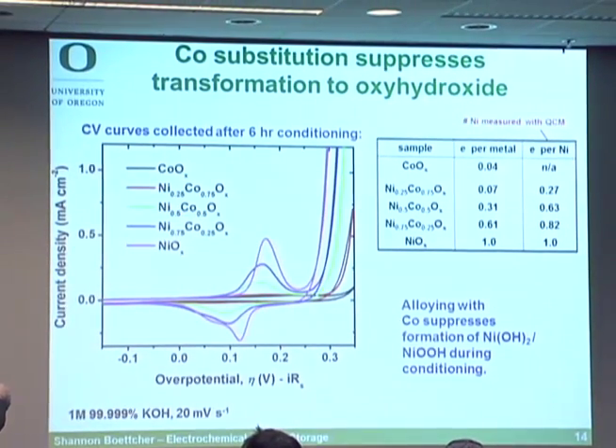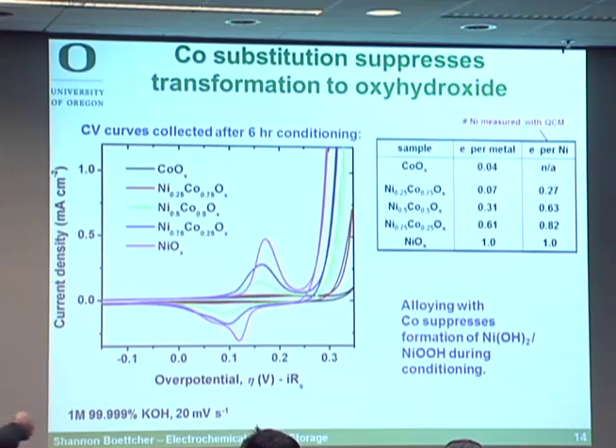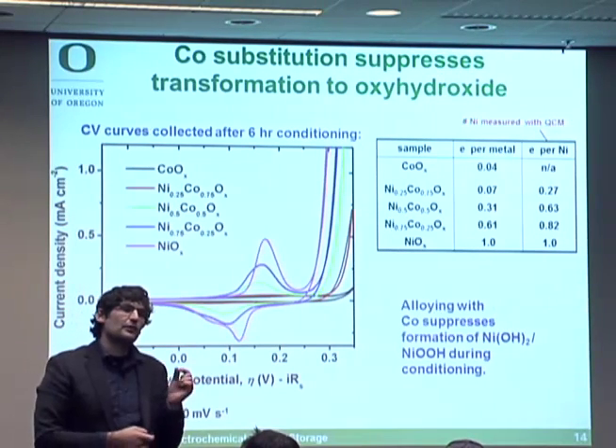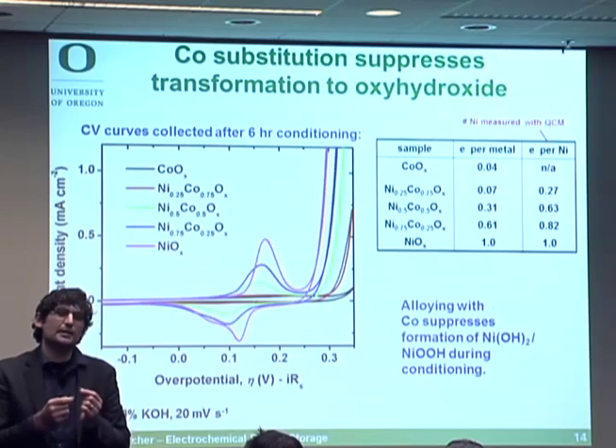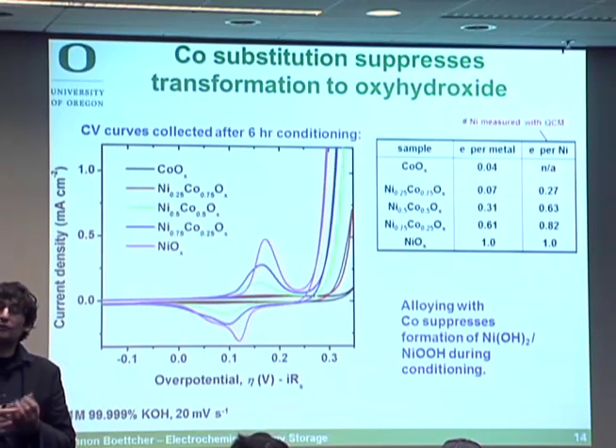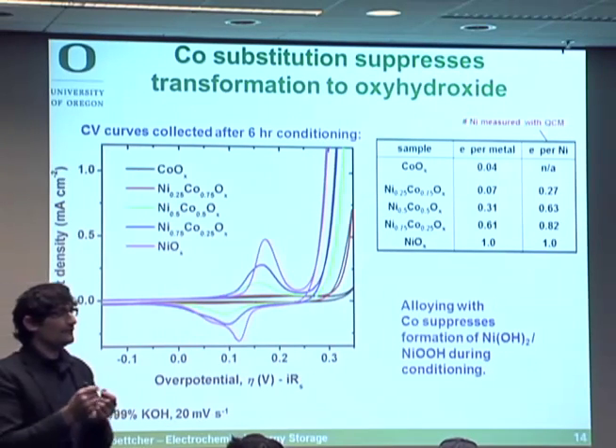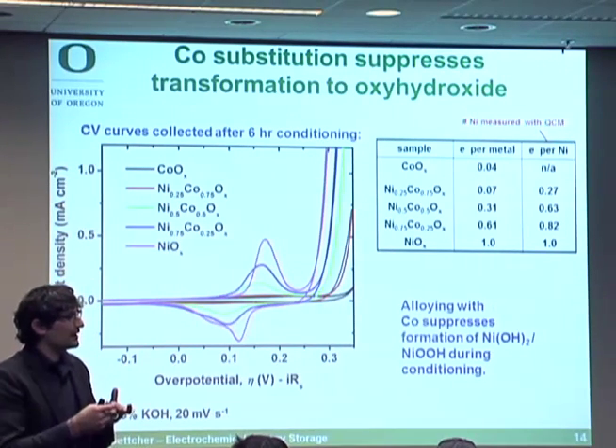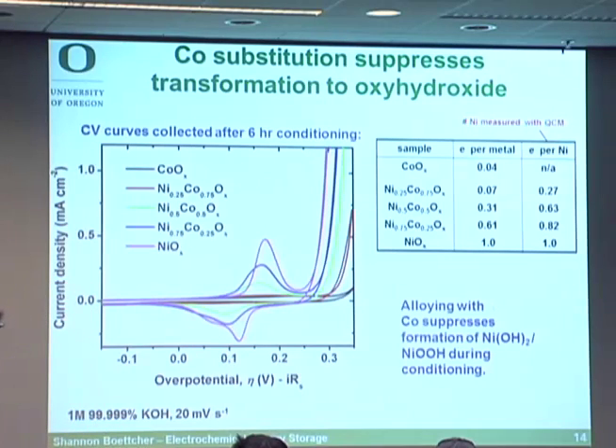And as you add more nickel, this feature gets larger. But if you actually measure the number of electrons that go into that oxidation wave and compare it to the total number of nickel ions that are in the film, because we can weigh it, we have it on this quartz crystal microbalance, we can weigh it and compare those two. What we find is that for the pure nickel oxide film, essentially every nickel atom is becoming electrochemically active.